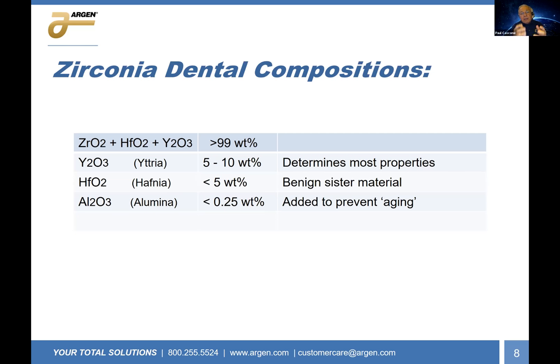The problem is that the material is not very aesthetic at that level. You need to bake porcelain on top of it or press porcelain on top of it. And in order to get a monolithic material, some of the early ones had no alumina at all and risked the aging factor. But as time went on, we learned how to control the alumina content to improve the aging and not impact the aesthetics.